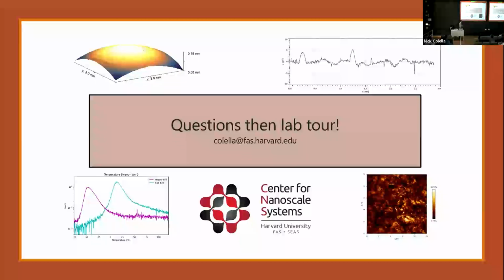How long does it usually take to run the scanning calorimetry? Yeah, great question. So we typically heat at about 10 degrees per minute and cool at 5 degrees per minute. So for a standard run, it's about an hour and a half usually. If we're heating up to like 200 and cooling back down to around 0, that'll be about an hour and a half. But you can do the calculation if you want to heat up higher. Heat at 10, cool at 5, and then you have a heat, cool, heat. Yeah, hour and a half on average.